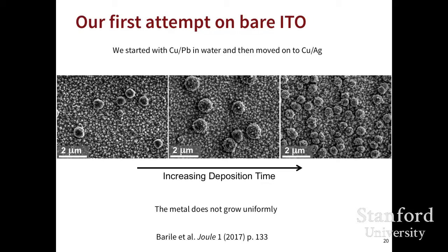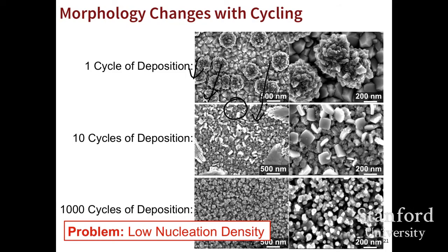Here you can see scanning electron microscope images, and you see that there are just particles of the metals plating, and it's not plating uniformly everywhere, and light is able to go in between the particles. And even worse than that, when we cycled it 1,000 times and looked at the morphology with SEM, we found that the morphology was changing a lot. And we're reasonably sure that that happens because we don't think we're able to completely strip the metal off of the indium tin oxide, and the residual metal influences the future growth.